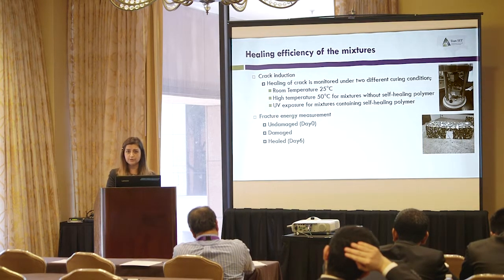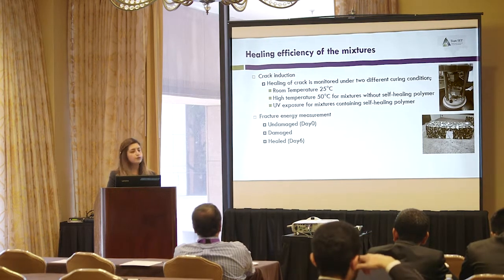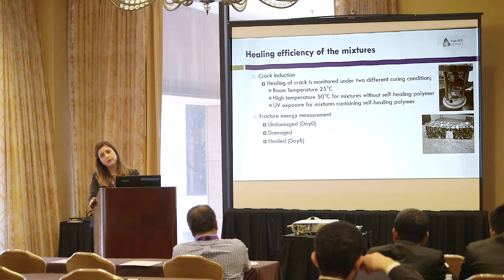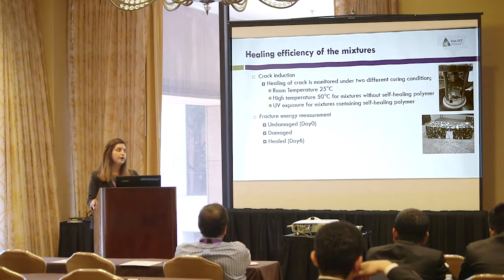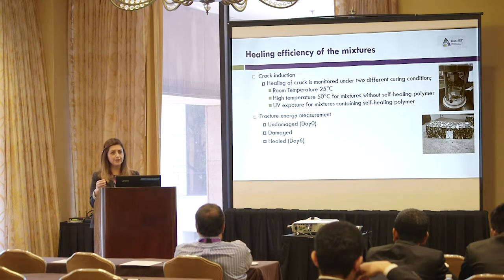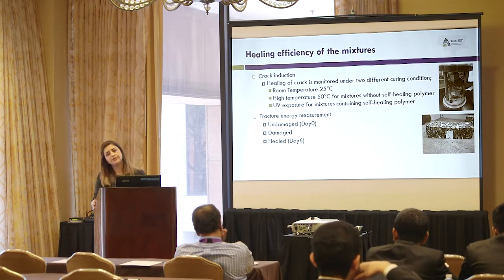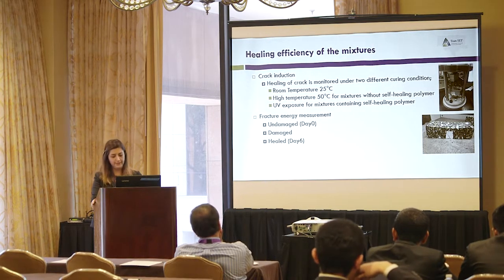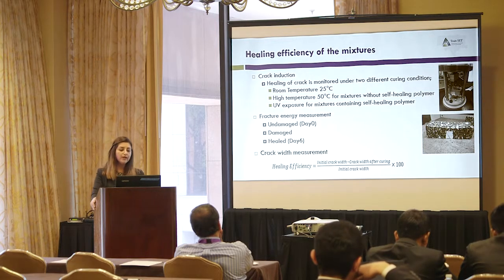We used 2 approaches to monitor the healing of these beams. In the first approach, we measured fracture energy, or the area under the load displacement curve, until the peak load. We measured the fracture energy for the undamaged sample, and then after creating the crack, we remeasured the fracture energy. So undamaged and damaged are both on day 0, and then after 6 days of curing, we remeasured the fracture energy.